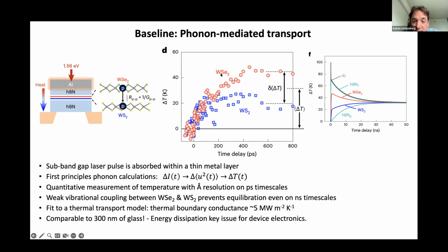Okay, so from these types of measurements and from a detailed heat diffusion model, the key input into the equation is the difference in the temperature between the two layers. We can extract directly information about the effective resistance. This is sometimes called the Kapitsa resistance. The inverse of this is called the thermal boundary conductance. And we get direct numbers for this of the order of 5 megawatts per meter squared per Kelvin.